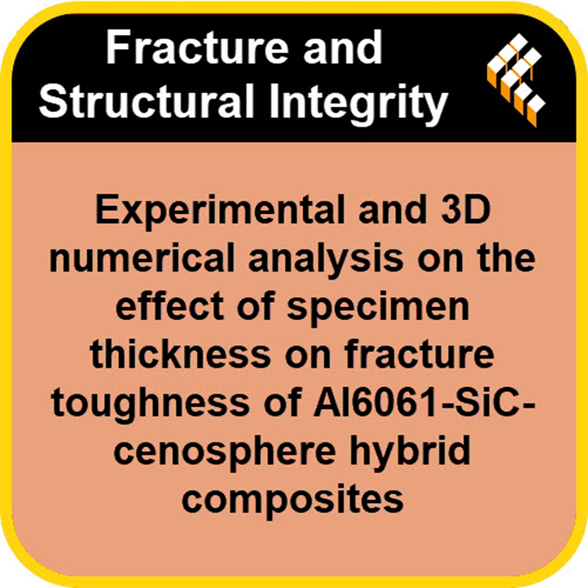Once that B/W ratio hit a value of 0.5 or greater, the fracture toughness value just leveled off. It stabilized, became constant. And based on the specific dimensions they used, the stabilization point happened when the sample thickness got above 12.7 millimeters, or half an inch. So why is hitting that plateau the definition of reliable data? Why is that constant value the one we trust? Because that stable minimum value is the plane strain fracture toughness. That's the real material property under maximum constraint. This value represents the material failing in its most constrained, most brittle state, which means its lowest toughness state. And when you're designing something safety critical, like an aircraft part, you absolutely must use this conservative lowest K value. It guarantees the structure can handle the worst case scenario.